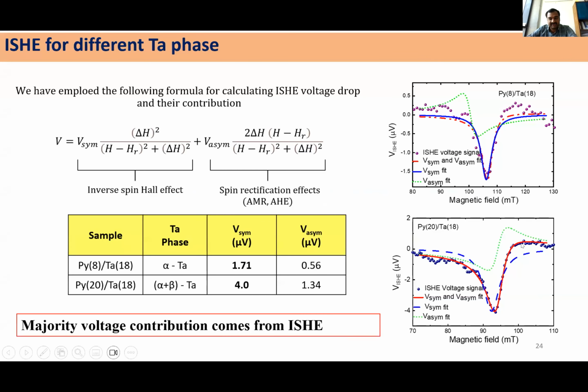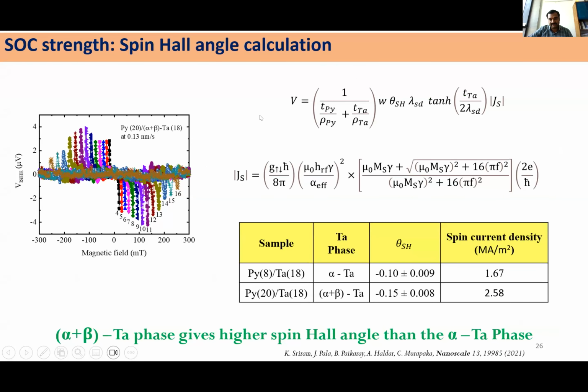This is our ISHE signal, the spin pumping voltage signal, which contains contributions from both the inverse spin Hall effect and the spin rectification effects, like AMR and AHE. When we measure this voltage, we only take the symmetric component. We completely ignore the asymmetric component. So whatever results we are fitting are due to the inverse spin Hall effect, not due to spin rectification, that is, AMR and the anomalous Hall effect.